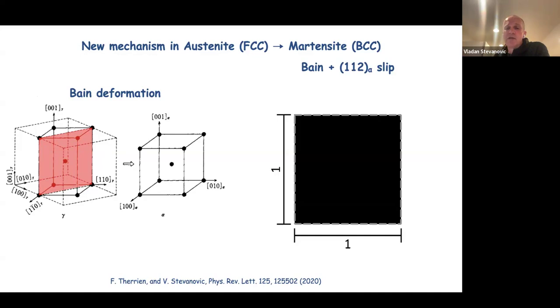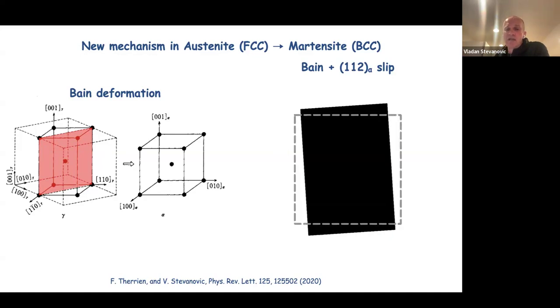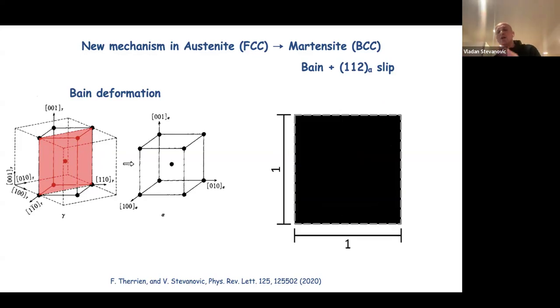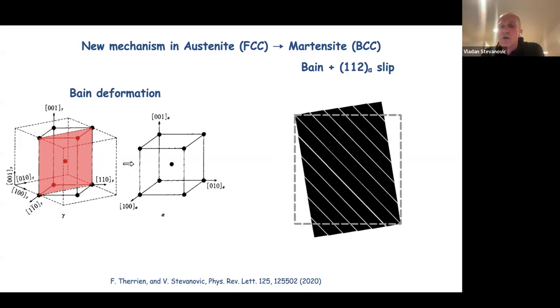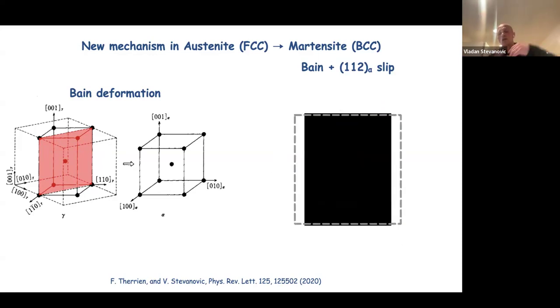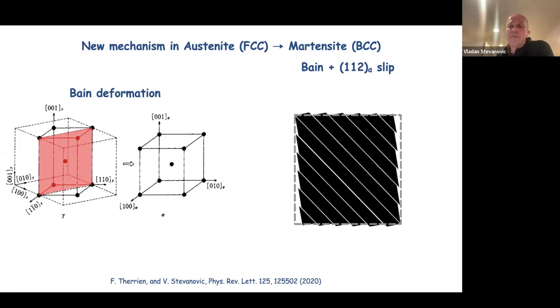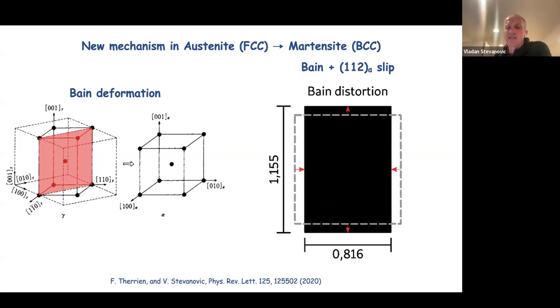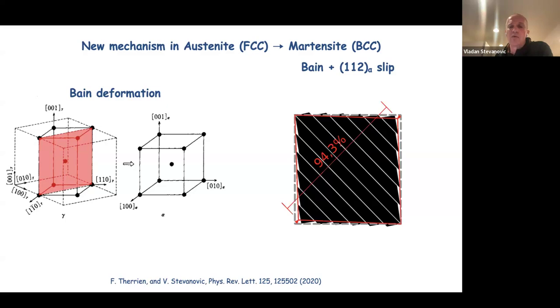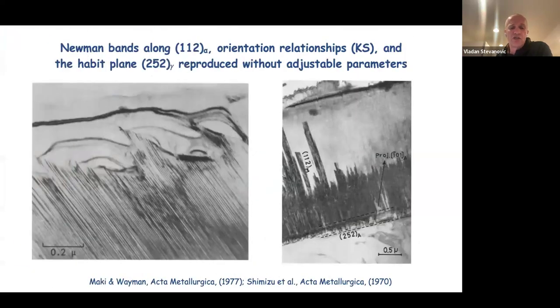And our mechanism can be explained like this. So the Bain distortion will produce a very large strain, but then the slipping process will pretty much slide these slabs relative to each other and then minimize the global strain. So that's why the slipping happens. And you can then go into the experimental literature and look for evidence of what is known experimentally. So these are two pictures of martensitic steels after the transformation from FCC to BCC has happened.